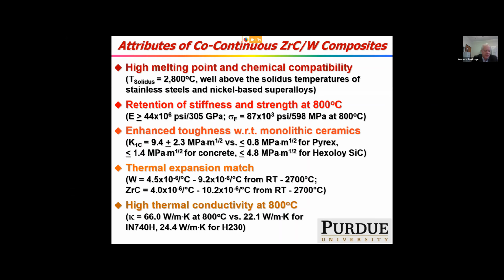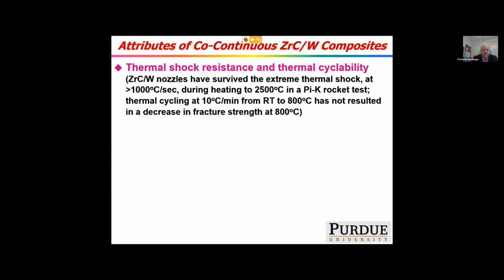As I mentioned, they're also thermal expansion matched, which is good for a cycling application like heat exchangers. And they're quite thermally conductive. We've measured the thermal conductivity at 800 C to be about 66 watts per meter Kelvin, which is something like 2 or 3 times higher than for stainless steels or nickel-based superalloys, which is a nice characteristic to have, of course, for a heat exchanger. So because of these thermal characteristics, they're quite thermal shock resistant.